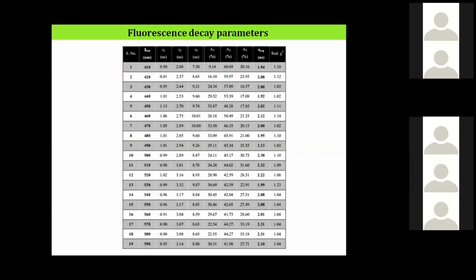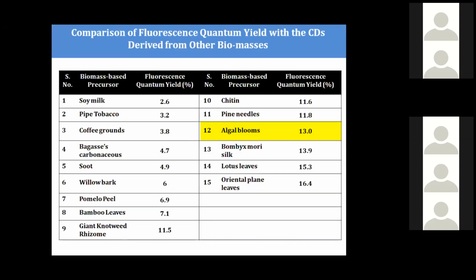Now one can also do a detailed analysis of fluorescence lifetime, and you can see that there is a triple component, a triple exponential analysis. One can look at it, it gives you a better fitting. So you always see the multi-exponential fluorescence decay of all these quantum dots.